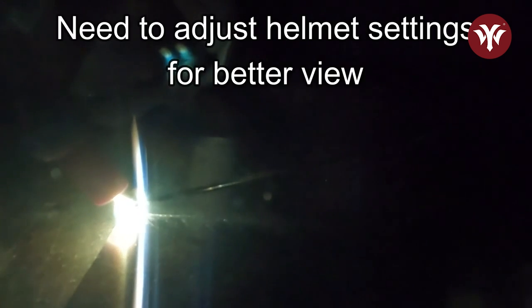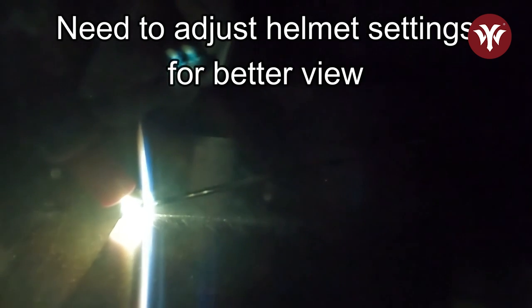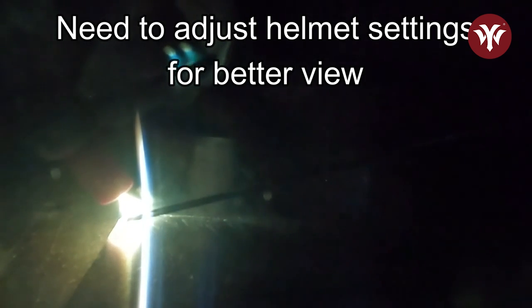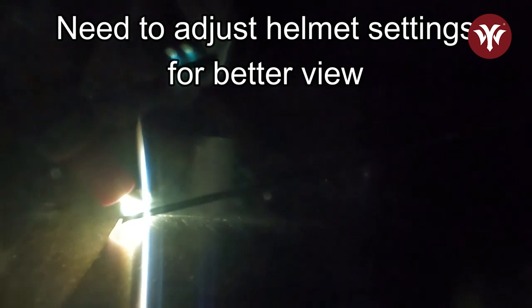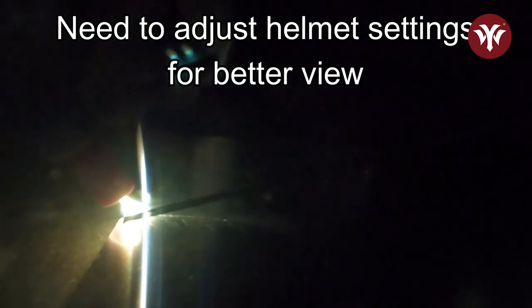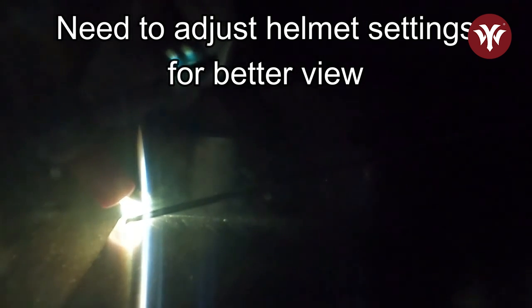All right, I hope you can see that. Starting to get both sides melted a little bit. Dab a little filler in, there we go. Now we have a puddle. And I hope you can hear me over the buzzing, but we can hold that puddle here indefinitely. That is the beautiful thing about TIG welding. I can back that current off, and you'll see the texture start to solidify, or I can bring that current back in. We'll get that puddle, and if you can see what I mean, it's a texture change.